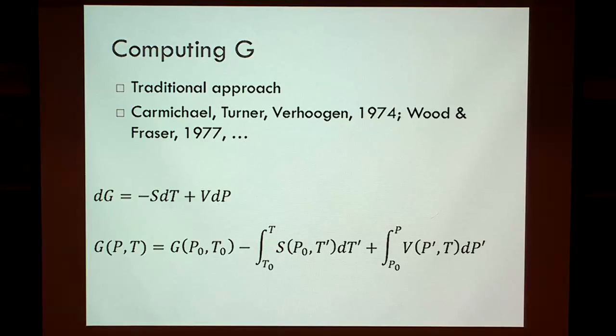Actually, you can measure it calorimetrically by looking at small changes in the energy of a sample as you heat it. It turns out you can work out the entropy from that, and you can integrate this very directly, almost directly from the experimental measurements themselves, almost. And this term tends to be small. Okay. But that's a problem for applications to the deep Earth. Yes?